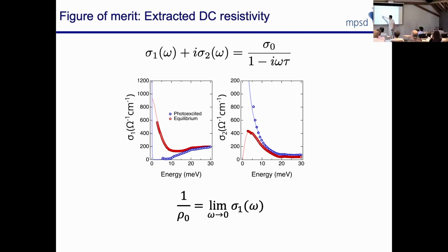When you take this data here, there is a range of possible scattering rates that are compatible with this data. The most optimistic situation, in which, let's say, sigma 2, you see it easier here, rolls over immediately here, is one in which the scattering time is the lifetime of the state, which is measured in the experiments. And I apologize, but I put here the most optimistic situation. In neither one of these cases is the scattering time infinity, because this is a transient state.